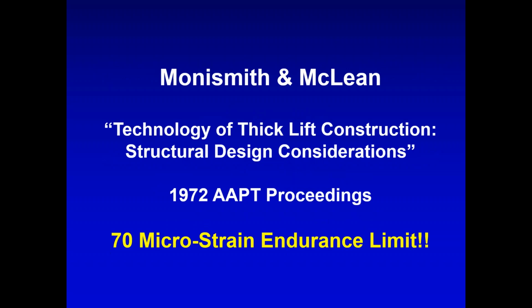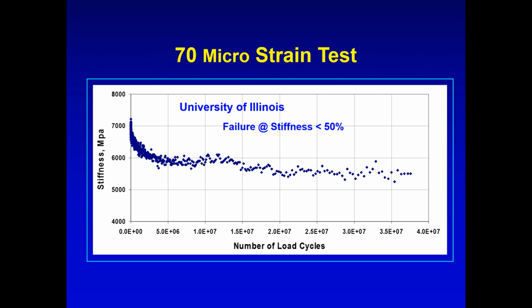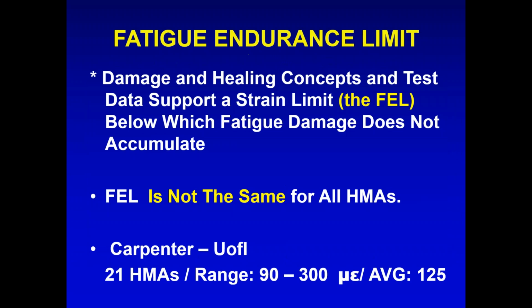Carl Monismith and a guy from Canada named McLean, back in '72, came up with this particular paper. They were suggesting 70 microstrain as a magic value. This is some work Sam did. Notice here, we're out here, what's that? That's 35 million. He's out there close to 40 million reps, and this particular mix went all the way at 70 microstrain. That's a lot of pounding, 40-some million. The fatigue endurance limit is out there.